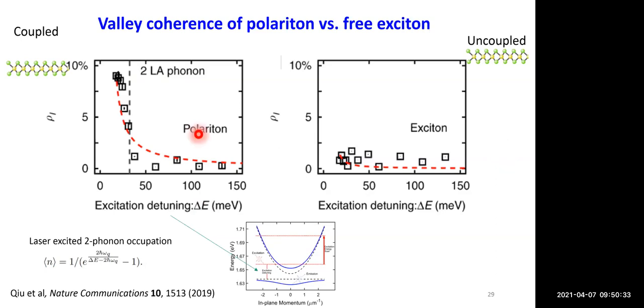So in our data over here, basically we have two parameters, which is the temperature that fixes the intrinsic thermal phonon bath, and that is what determines also your maximum observed valley-polariton coherence. But again, there is scope to increase this degree of coherence if you increase the energy, the resonant excitation closer and closer to this exciton mode, because right now the minimum laser detuning is around 20 meV, which is still quite far from your exciton resonance.